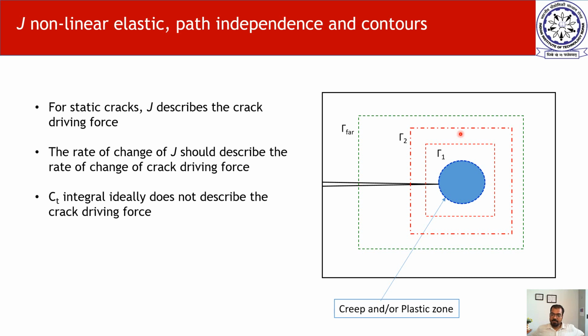Now look at a cracked specimen, and let us say that there is a creep zone. So initially, if the material is elastic plastic and the stress applied on the system is higher than the yield strength, there will be a plastic zone. But with time, if you keep the force constant, the creep zone will increase and it will encompass the plastic zone. Now if you have contours like gamma 1, gamma 2, gamma far, which are encompassing that deformed zone, then the value of J integral for all these contours will be same. The rate of change of J integral will also be same, and they will be defining the crack driving force, because the crack will be moving with the deformed zone as long as the deformed zone is inside the contour. And therefore we can use nonlinear elastic theory for small scale creep condition.